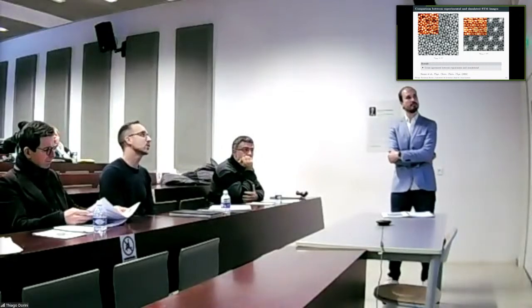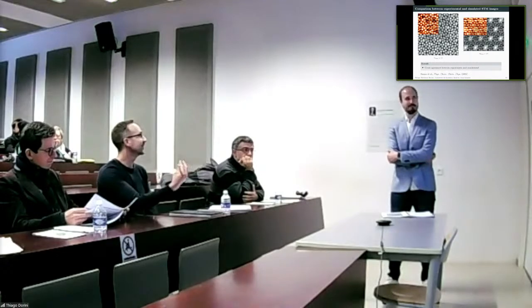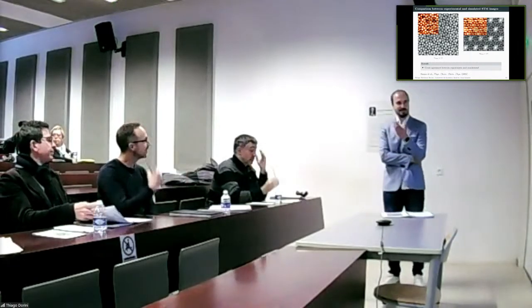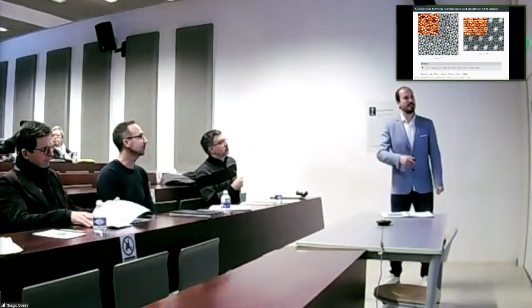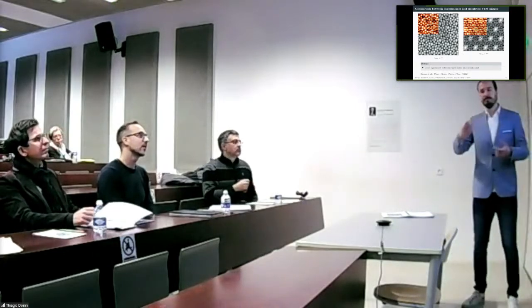When you, for example, look into the pores of the squares, there must be 4 titaniums inside. Why don't you see anything? Yes, it's quite surprising for me as well. But we tried to do this calculation changing the bias. And in some cases, for instance here, it's also possible to see some protrusion that might come from the titanium atoms as well.